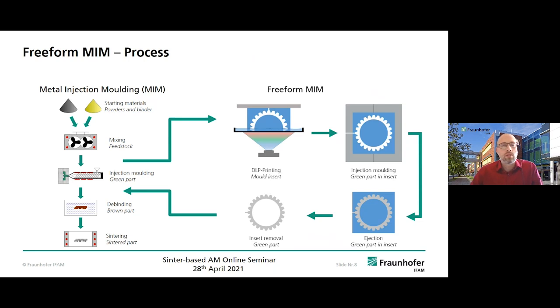Then this part fits into a base mold, as you can see on the upper right side, and the feedstock in the injection molding step gets injected into the space that is available by this green part, by this printed part. And this printed material can be removed chemically by a hydrolyzation step and a removal of the hydrolyzation products. And then you basically have your green part, which goes back into this standard process chain of debinding and sintering.